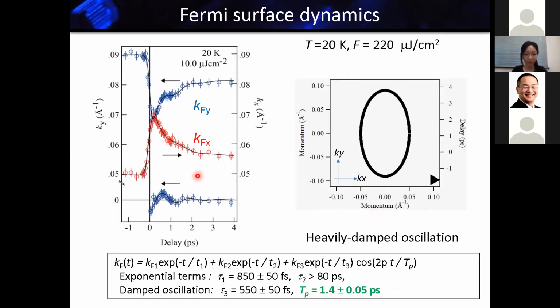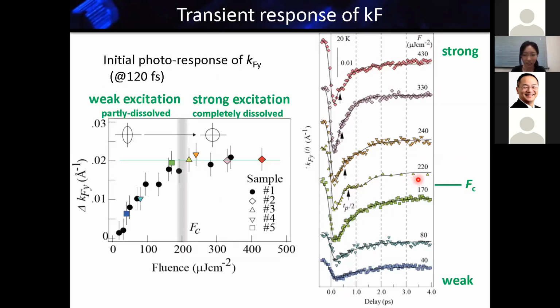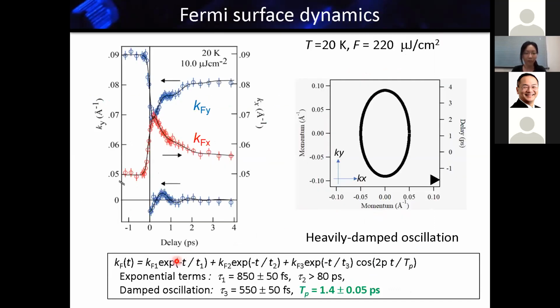Okay, so this curve is the one at the 220 fluence here. Here we can clearly see that the Fermi momentum, in the case of the longer Fermi momentum, first decreases, starts oscillating, and recovers. For the shorter Fermi momentum, it becomes longer and then also shows a slight oscillation. We try to extract this oscillation part by fitting with this function.